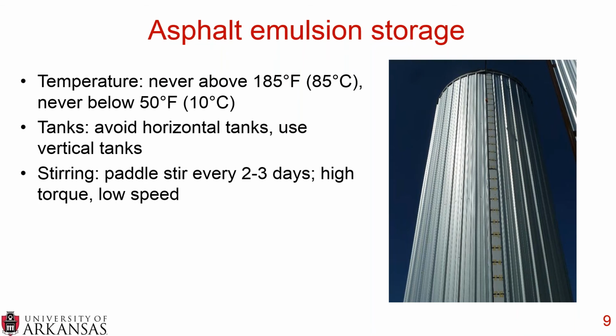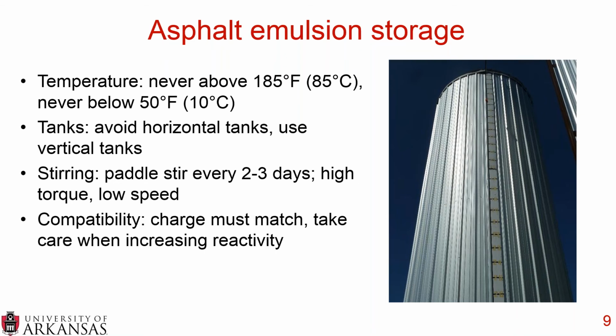And these are very high torque paddles, low speed. You don't want to inject air into there to try and circulate it roughly. You want to be very gentle with your asphalt emulsion, or else you could damage it. And then Chris also spent some time talking about charges and reactivity of asphalt emulsion.